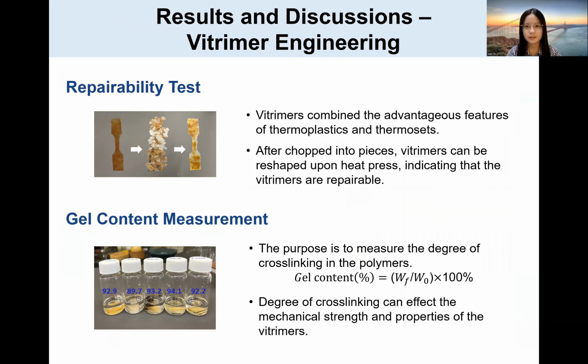And after the vitrimers are formed, I further test the repairability and the gel content. Repairability is important because if it's repairable, it can be reused and the life cycle of PLA waste is elongated. So how did I test the repairability? I cut the sample into pieces and further reprocessed it through the heat press method, as you can see in the picture on the left. And the results turned out to be positive. The model can be reformed, and also the tensile strength is just as good as the pristine model.